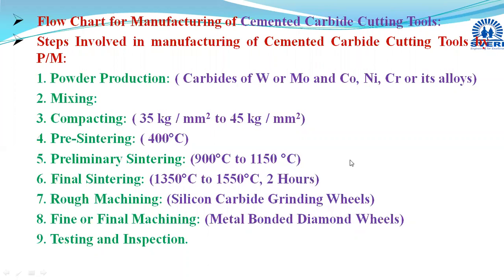Now in this final sintering at this high temperature range, what will happen? Whichever cobalt particles are there, it may be separate cobalt metal, or in the form of alloy, that cobalt will start melting and goes into the molten form. This molten cobalt will create a bond, or act as a binder to join tungsten carbide particles or molybdenum carbide particles. Means the bond will get created, and this process is termed as cementation process. Cobalt melts, and it joins or creates the bond between tungsten carbide particles or molybdenum carbide particles. This process is termed as a cementation process.